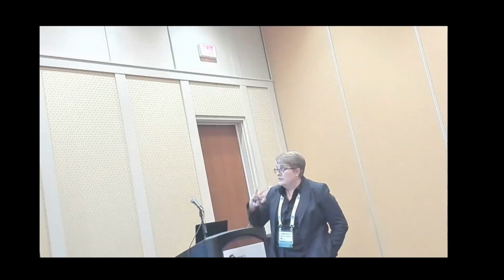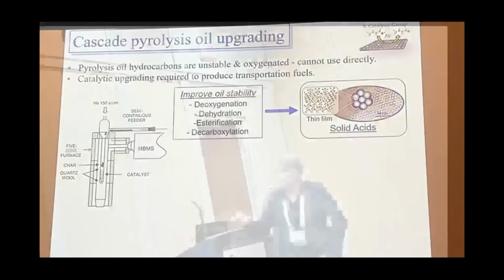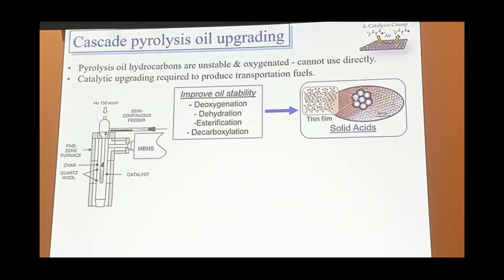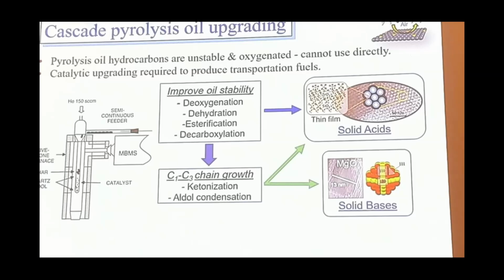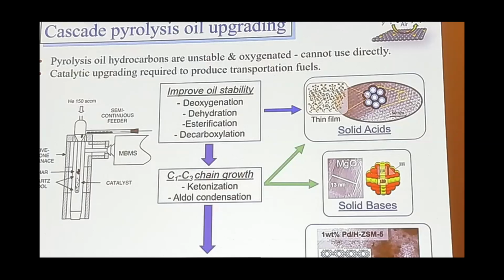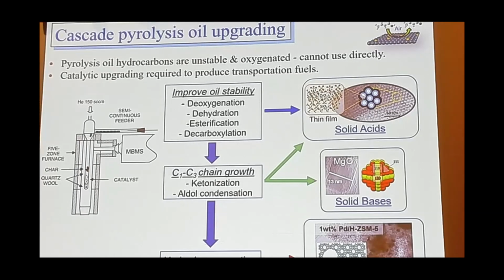So I'm not going to talk about any details of the catalysts and the pre-treatments, but it can give you an idea of the type of reaction you're targeting. So, for example, esterification, decarboxylation would be a way to remove acids from the oil. Again, things like sulfated zirconia samples are very good at doing those reactions. Ketonization is another approach which can allow you to grow chains while also removing acidity from the reactions. And likewise, aldol condensation. So here you might be looking at solid bases or doped solid bases in order to grow chain length via aldol condensation. And then the final step really is hydrogenation to remove the oxygen from all the components. And there, the use of metal doped solid acids is something that's of great interest.